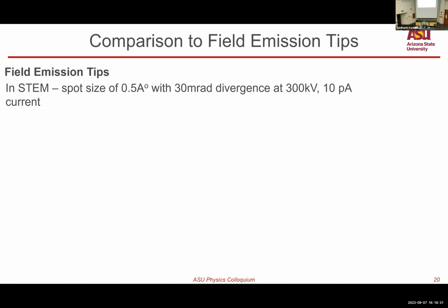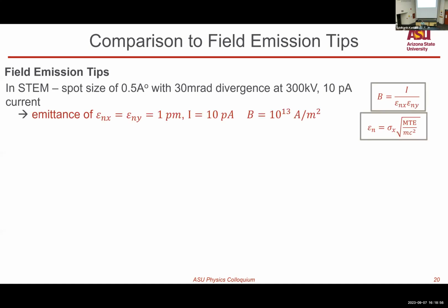Okay, now a quick comparison to field emission tips. I told you these field emission tips are the brightest sources of electrons that we have so far. If you consider a scanning transmission electron microscope, you can get a spot size of 0.5 angstroms with 30 milliradians divergence, close to the state of the art that's possible at 300 kilovolts and 10 picoamps. If you translate that to emittance and brightness, it translates to an emittance of about 1 picometer with a current of 10 picoamps, giving a brightness of the order of 10 to the 13 amps per meter square.